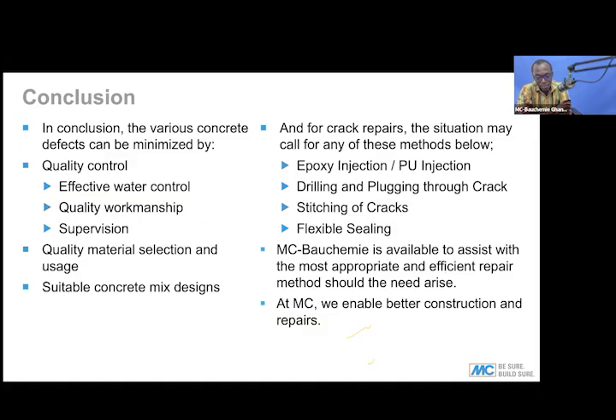As I mentioned earlier, if you have concrete where you need to work the surface, like a floor slab, you want to finish it properly, and you are casting larger areas, like a warehouse of, let's say, 10,000, 15,000, something like 2,000 square meters. If you don't use a retarder and you cast the concrete, by the time you come back to work on the surface, it's already dried. That is when you end up putting a lot of water on the surface, because you want to get the surface workable. But when you have a retarder, it gives you the freedom to cast large pours and allows you to work on it smoothly without any defect. So in that sense, it can help.